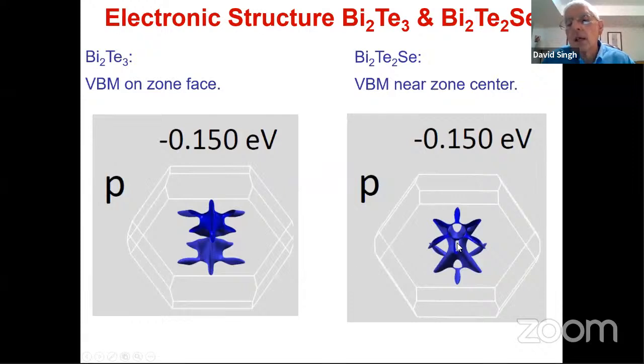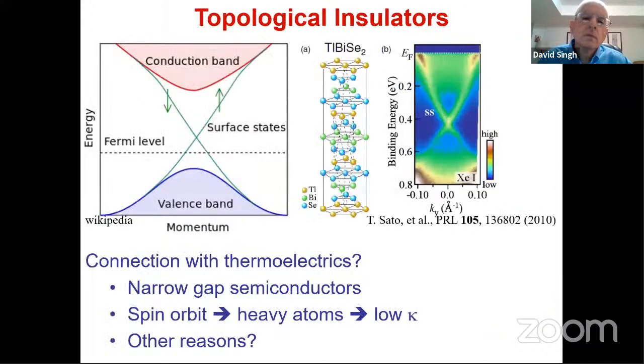If we could keep this band structure and increase the band gap, then we could obtain the highest ZT. But we couldn't. And so why is that? Why is it so sensitive? If we take some of the tellurium and replace it by a very similar element, selenium, the band structure changes very, very much. Why is that? And so that leads us to the topological insulator.